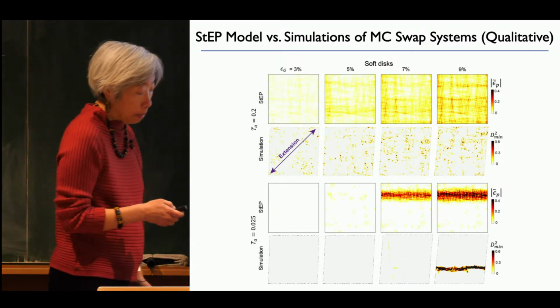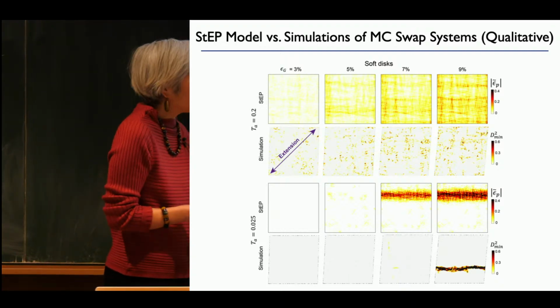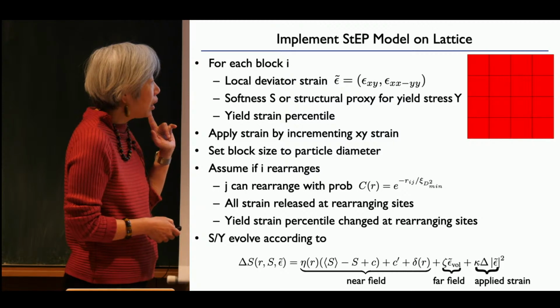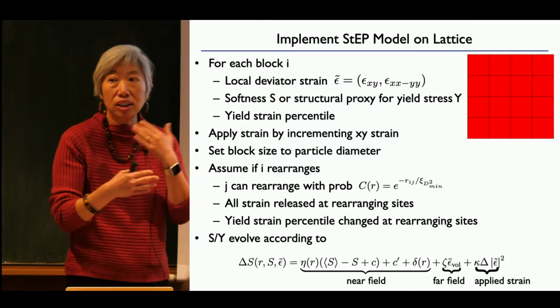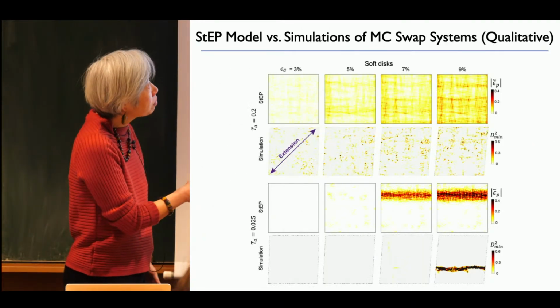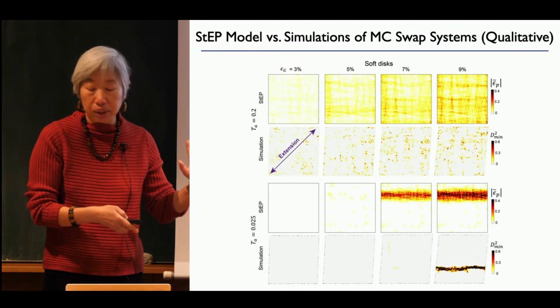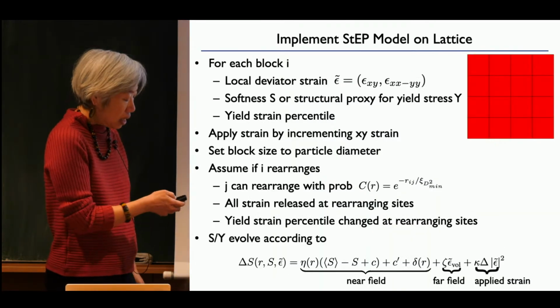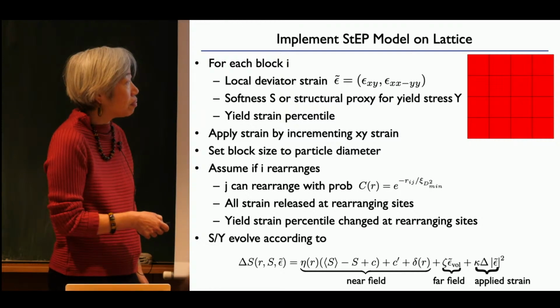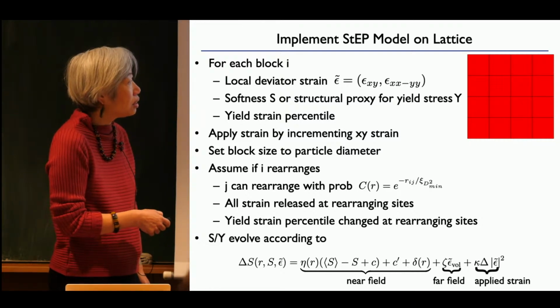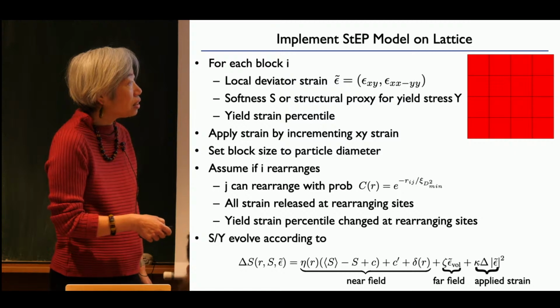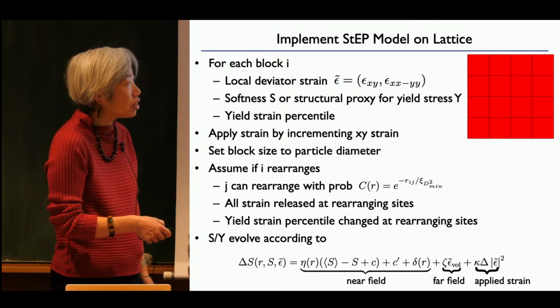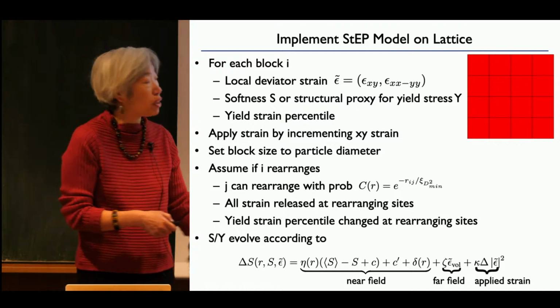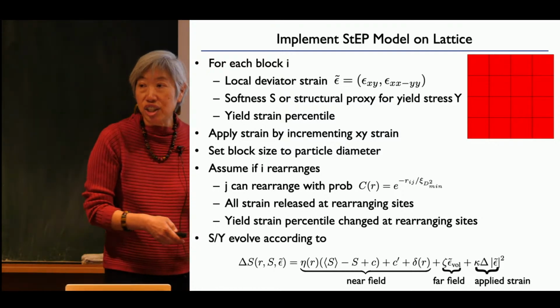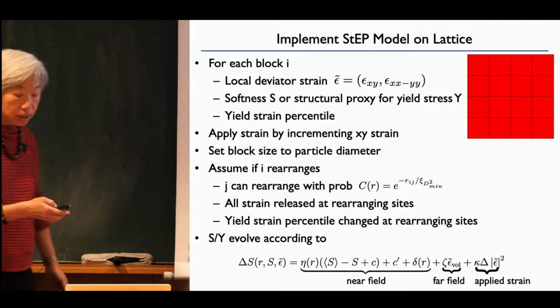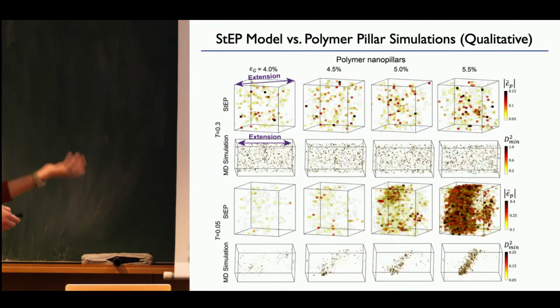And I should say that when we do this interplay, we work this out for all 6 systems. In other words, for these 2 systems, we have worked out that interplay separately. But what we find is that, in fact, for these 2 systems, everything is the same. The decay, the proportionality factor for the volumetric strain, the proportionality for the applied strain, how these change softness is identical for the 2 systems. So that's good. That emerges. We're not putting that in by hand.